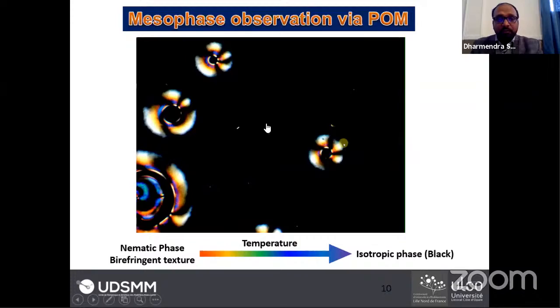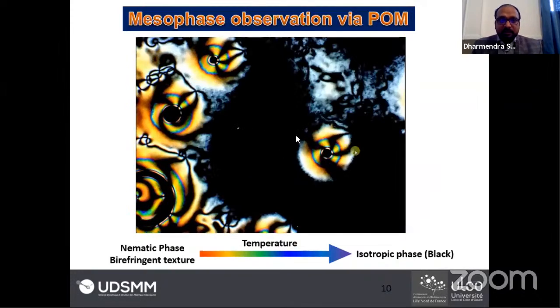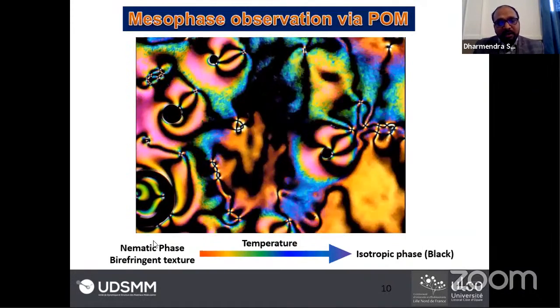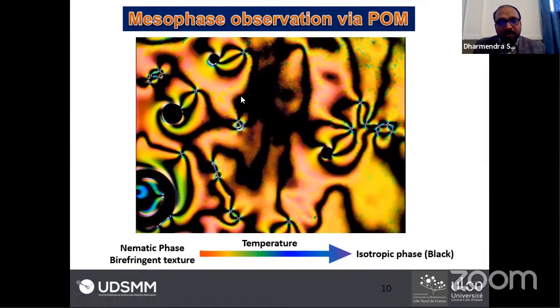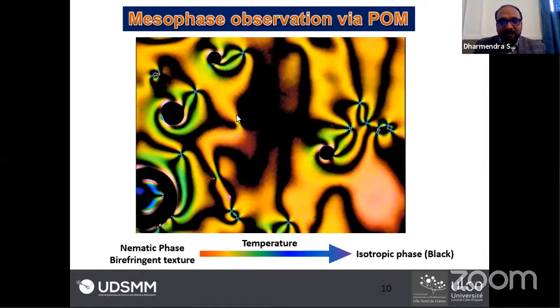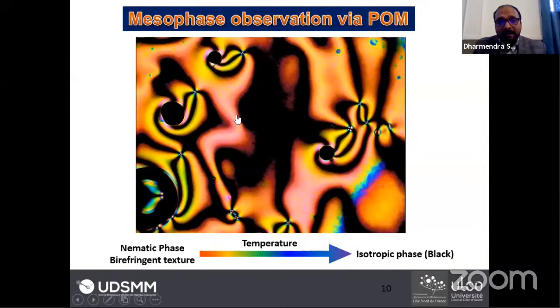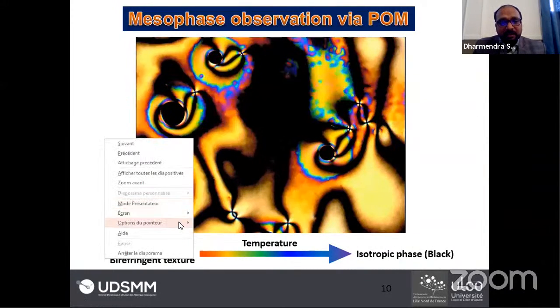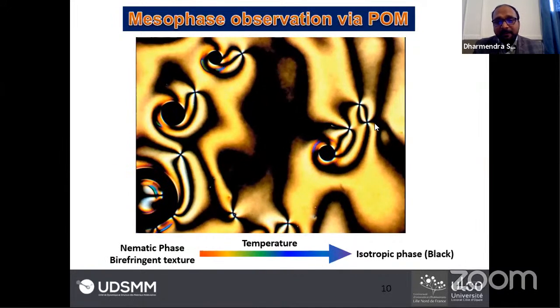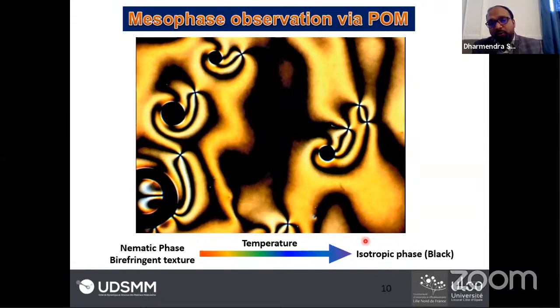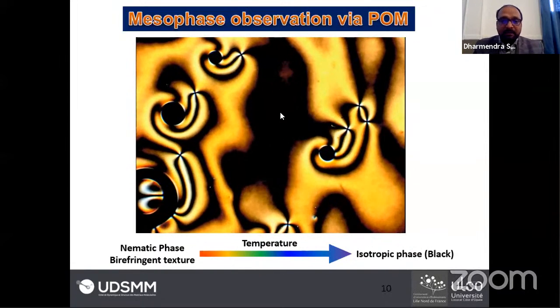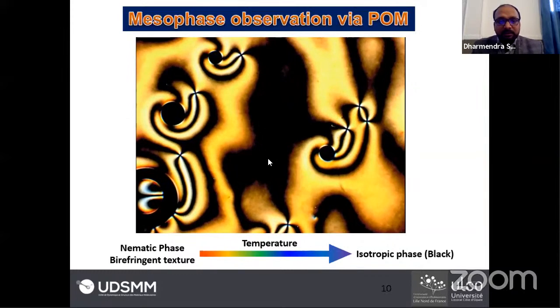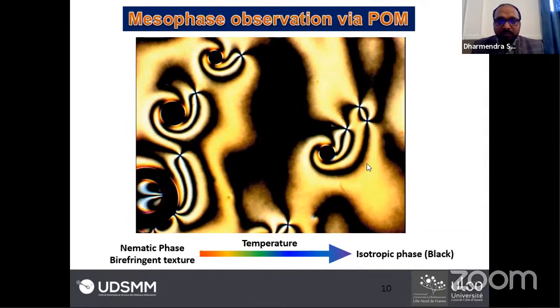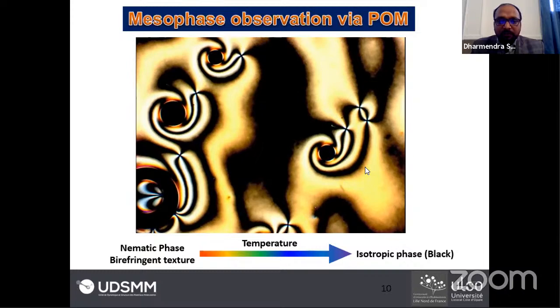So here I will show you how you can obtain the mesophase. When you heat any nematic compound, you can obtain a very fantastic birefringent texture. And with respect to temperature, you can obtain a thread-like texture, especially the defects as well. And when it goes to the isotropic phase, it becomes completely black. I think it should take some time to go to the isotropic phase.